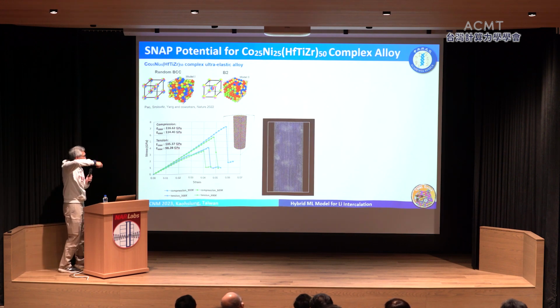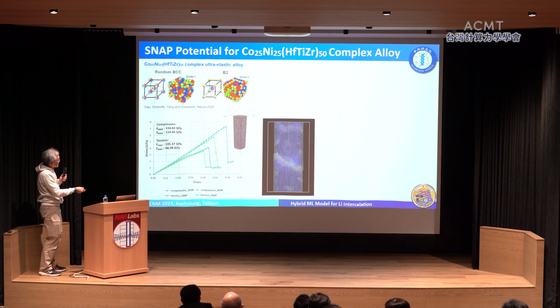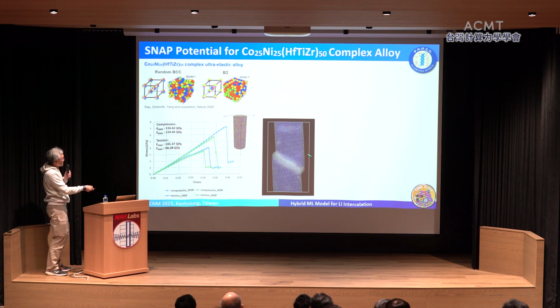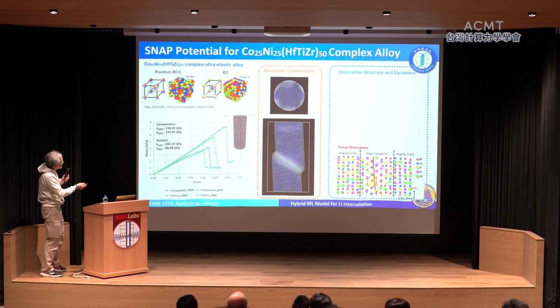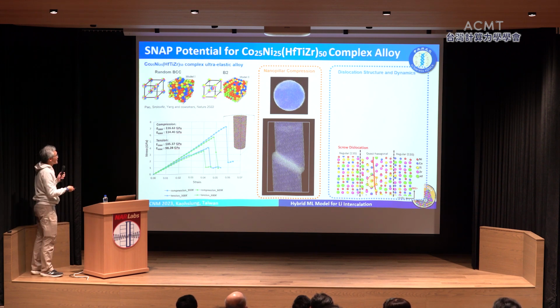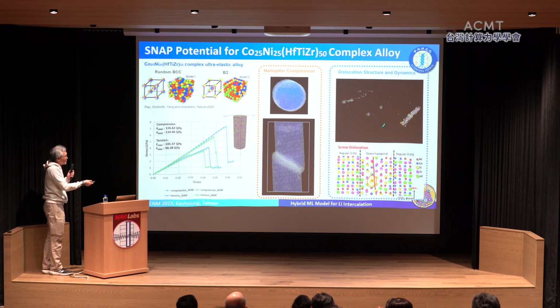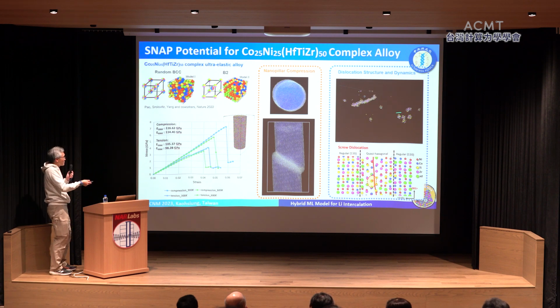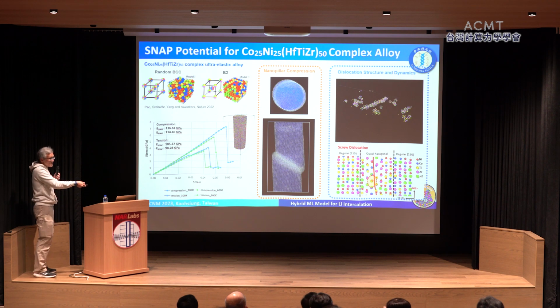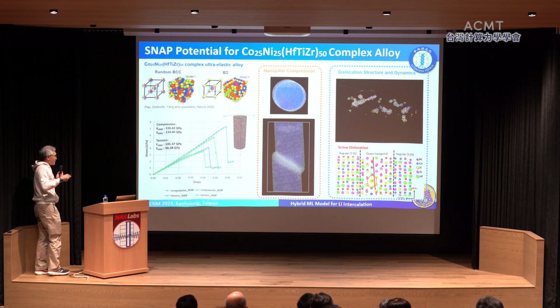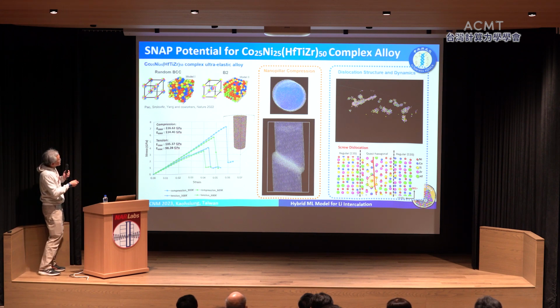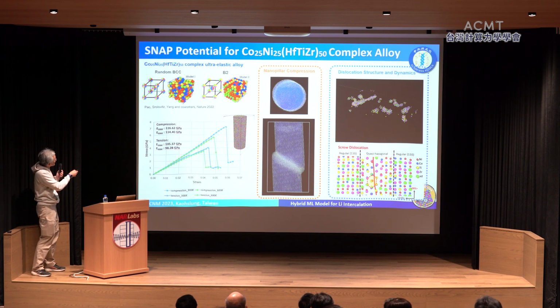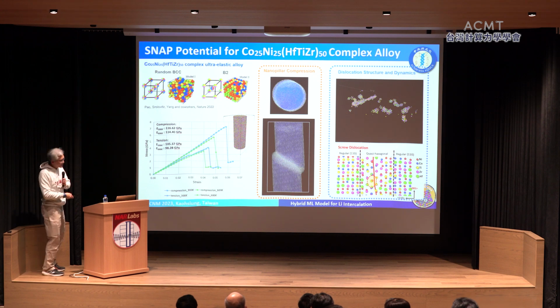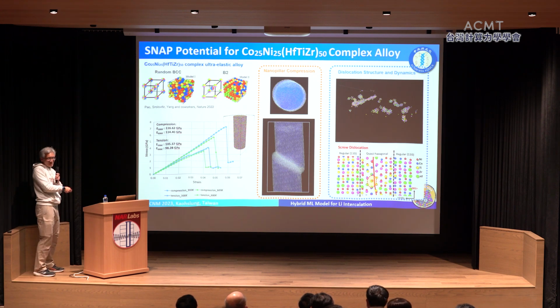And this is the simulation of a compression of a nanopillar of this alloy. You can find dislocation nucleation and the formation of an amorphous shear band. This is identical with the experimental observations. Viewing from the top, you can see dislocation propagate through this nanopillar. We can also simulate dislocation dynamics, so you can see dislocation glide through and leave a bunch of defects behind. We can also identify the core structure of a screw dislocation and edge dislocation. And the Burgers vector, which I didn't mention in my slide, predicted from the neural network, from this SNAP potential, is the same as that observed from experiments. And we didn't put the structure with dislocation into the training set.